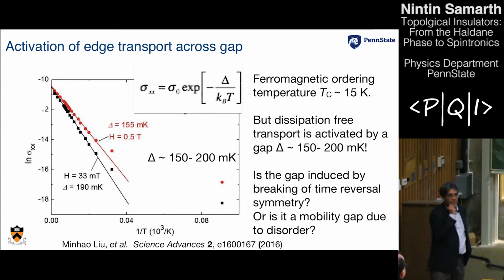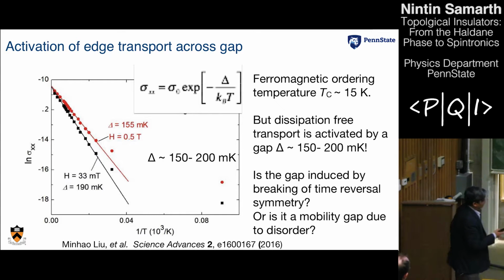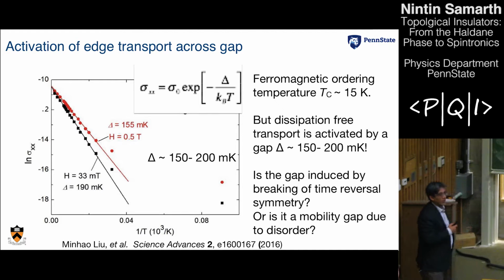And here is another puzzle. The magnetic ordering that we see in these samples typically occurs at about 20 Kelvin or thereabouts. These are the samples that show the best quantization. So 15 to 20 Kelvin. How do you measure the gap? Well, the way you can measure the gap is that you look at where Rxx has reached a minimum, okay? And then you measure that as a function of temperature.